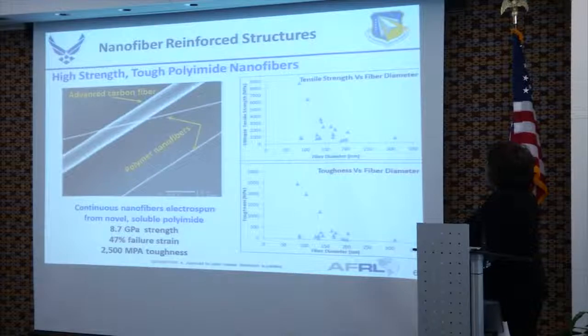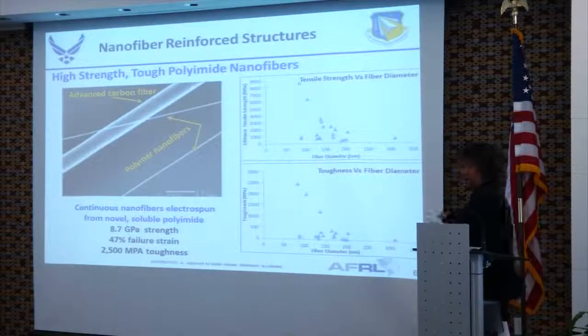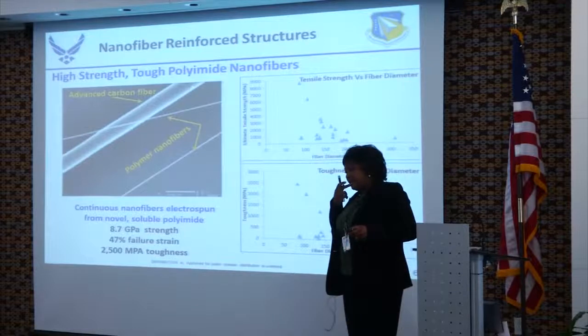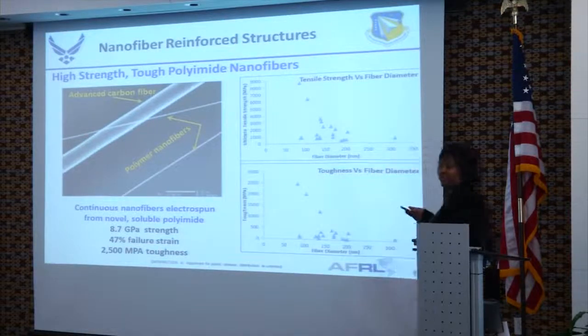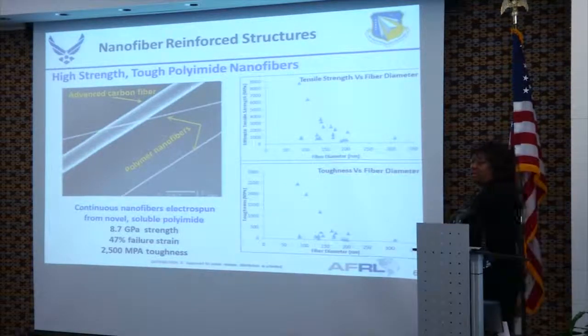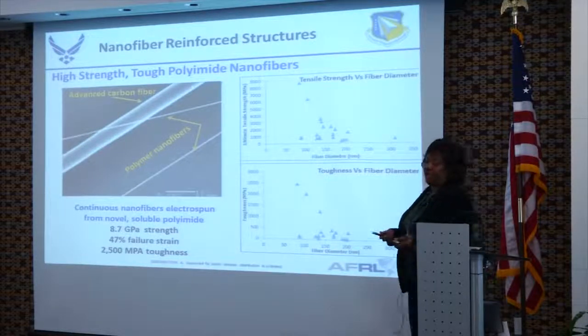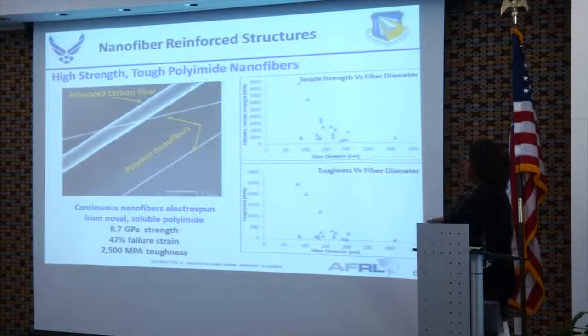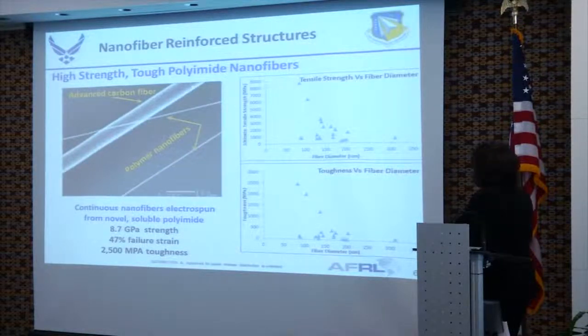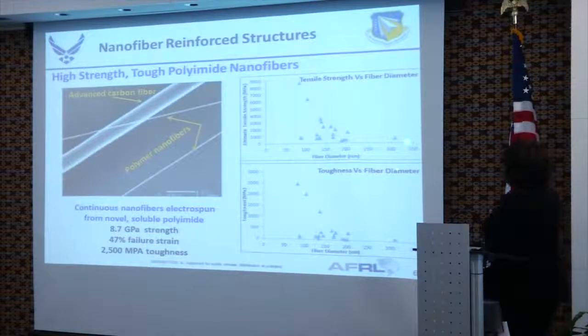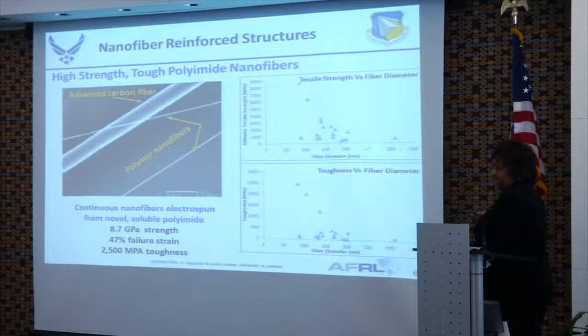In this example, the process, I should step back and say, is electrospinning. Electrospinning is where you spin a fiber in the presence of an electric field, typically with voltages on the order of 10 to 20 kilovolts, to spin these polymer nanofibers. And what he's seen is that at a threshold of about 400 nanometers in fiber diameter, you see a really nice increase in the tensile strength of these nanofibers.